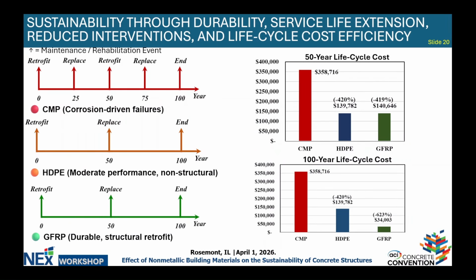Through this study, it's also important to understand what HDPE liners, GFRP slip liners, and just the CMP itself as slip liners can do to these systems for composite action in terms of rehabilitation and maintenance events. So each arrow that you see there is one of those events, and you see for CMPs, which are primarily corrosion-driven failures, many of those replacements, a retrofit, replacement cycle that happens. And HDPE, which is still moderate performance but non-structural in its essence, you see the replacement not happening too many times as with the CMP.